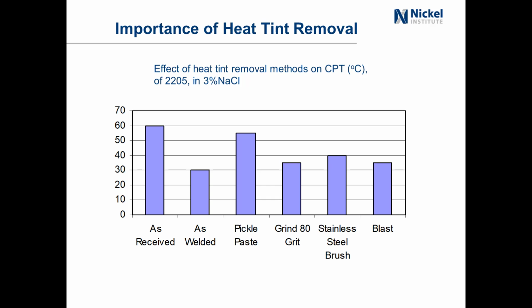But if you weld it and you leave the heat tint on it, it'll start pitting at about 30 degrees C. You can almost restore that back to the original by pickling it, and you can also improve the pitting resistance by grinding or stainless steel brush or blasting, but this wouldn't be allowed in a food application because you're going to have a surface finish that's greater than the 32 microinches allowed.